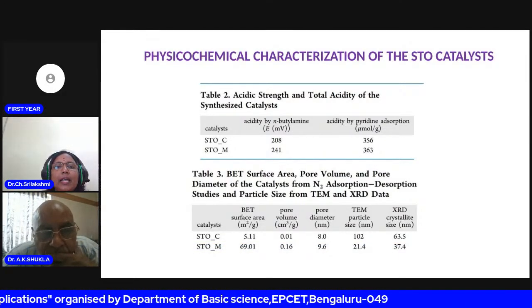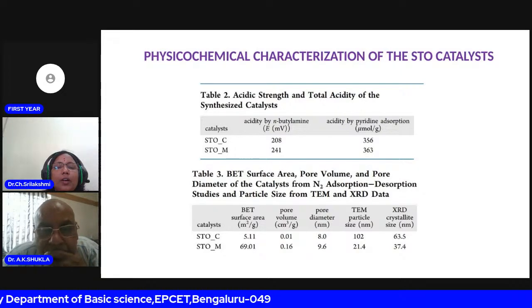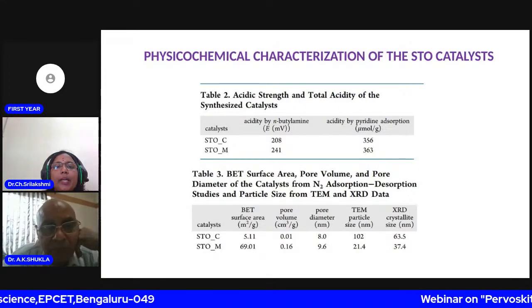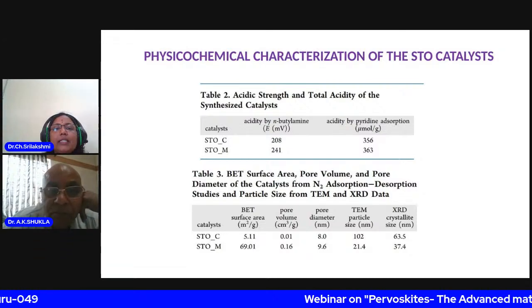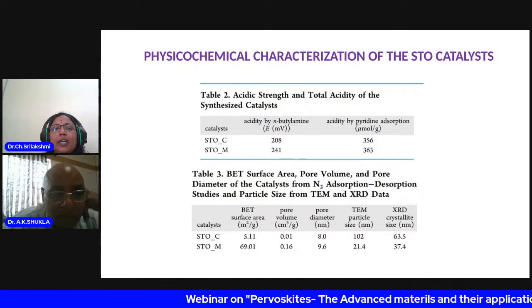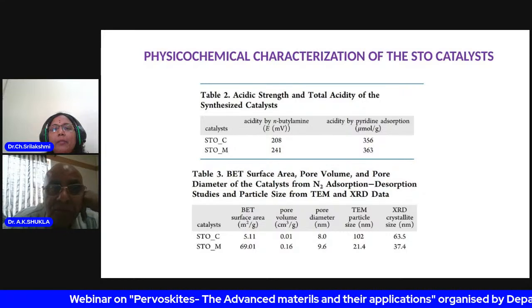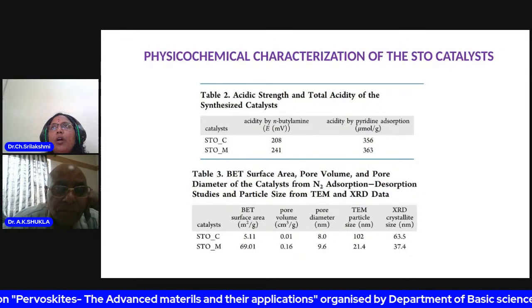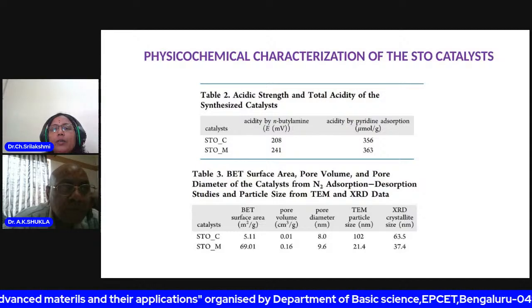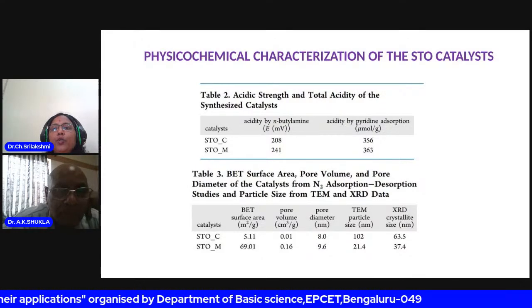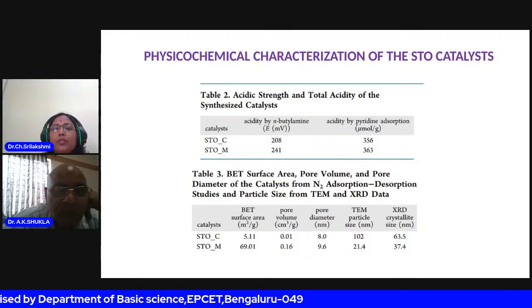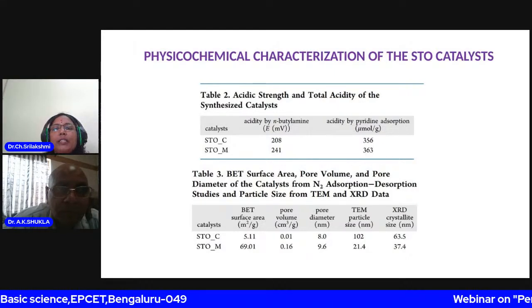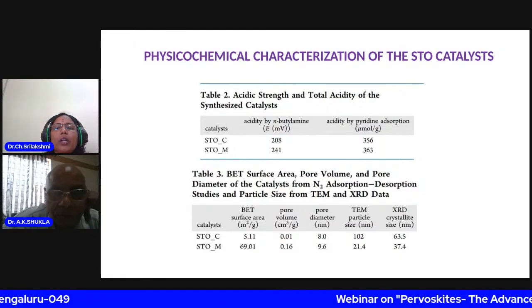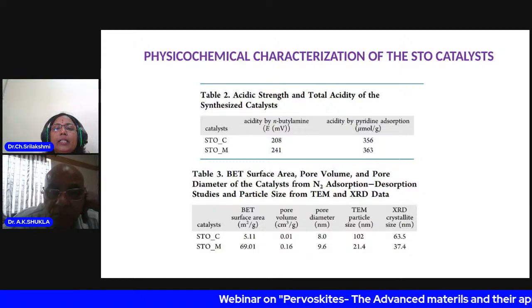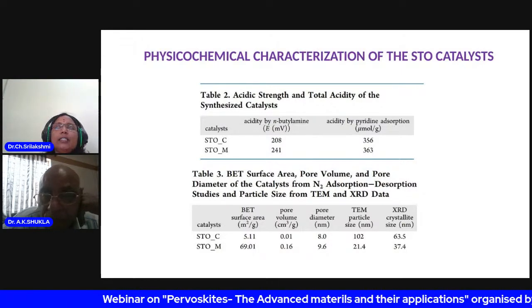That's the reason: you can see the surface area is just 5 for STO prepared by the conventional method, whereas this one is 69. The pore volume is almost 10 times higher, and the pore diameter shows both are mesoporous, because pores between 2 and 50 nanometers are called mesoporous materials. The particle size is 102 nanometers here, whereas this one is 21.4, and the crystallite size is also smaller. This is the beauty of this microwave synthesis method.